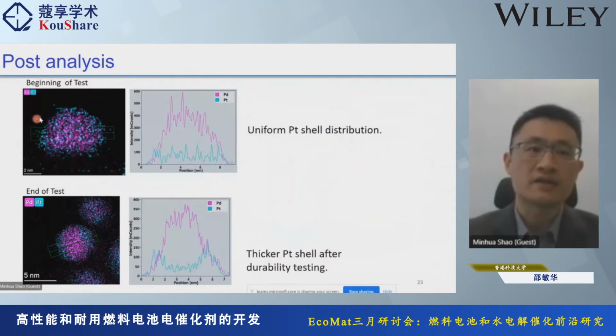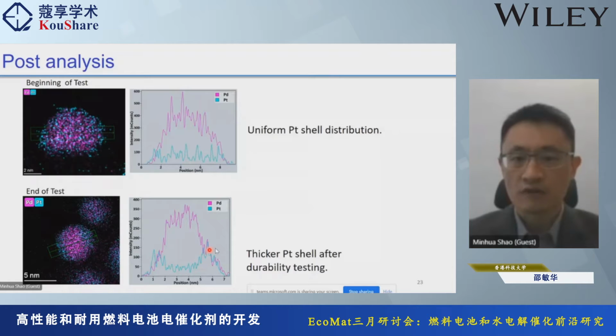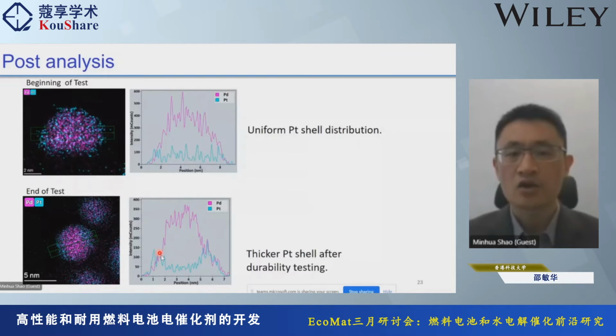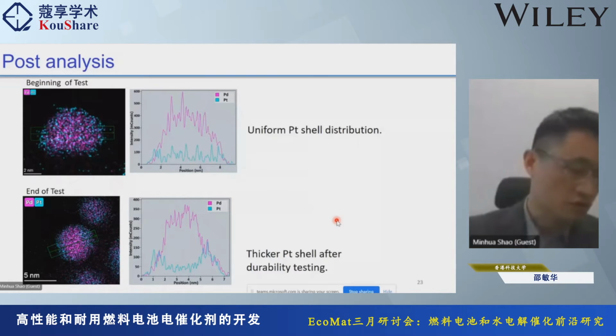Okay, and this is a post-analysis. This is the beginning of test of the core shell. You can see this is a uniform distribution of the platinum shell. After these 30,000 cycles, we still have this core shell, but you can see that the thickness of the shell increases. Okay, so that means you can still remove some of the palladium in the fuel cell testing, but with this durability testing, the platinum grows thicker and thicker, and further protects the core. Right, so the final core shell structure is still there.